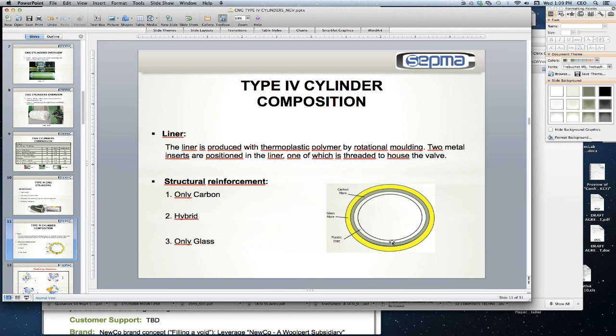This is a schematic that pretty much illustrates what I was just saying. You have an inner plastic liner, which is the inner ring shown here. You typically then have a carbon fiber layer, which represents your structural component. And typically, we will finish it off with a glass fiber layer, primarily for impact resistance. Carbon can be quite fragile and not very good under impact conditions. And obviously, these products have to survive, obviously transportation, but certainly also during service, it's not unusual to knock them or somehow dent them, and that's what the glass fiber primarily does in this case.